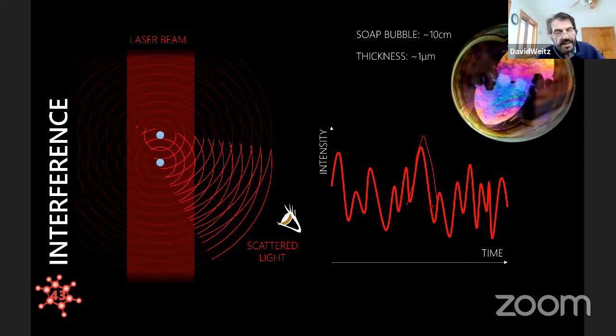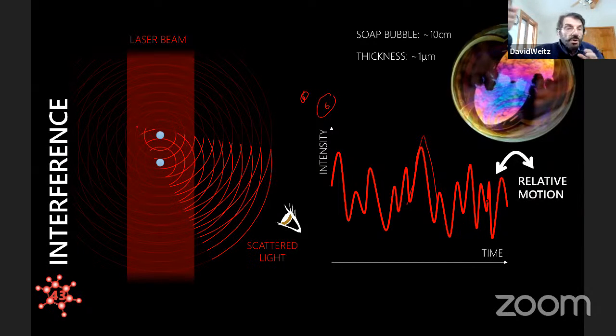And this is a very standard technique. It's very sensitive to the motion. Normally what it does is it measures the relative motion of just some collection of particles. The way it does that is you look at the speckles and you do a correlation function. You measure a single speckle. This is what it looks like as a function of time. You don't know whether the intensity is increasing or decreasing because you don't know exactly what the scattering is, but you know that the intensity is changing. You can see that it changes when the particles move with respect to each other some fraction of a wavelength. A full wavelength is this much. Some fraction of a wavelength is how much you can detect.